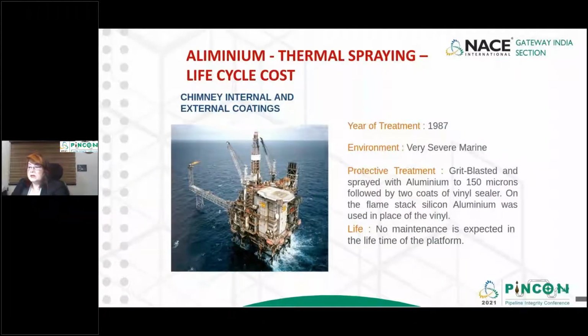Chimney internal and external coating was done by aluminum spray coating in an offshore platform, where the top coat was vinyl sealer, and on the flame stack silicon aluminum was used. No maintenance is expected since 1987.